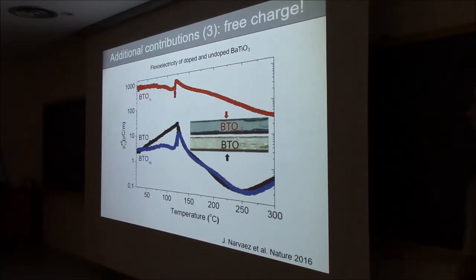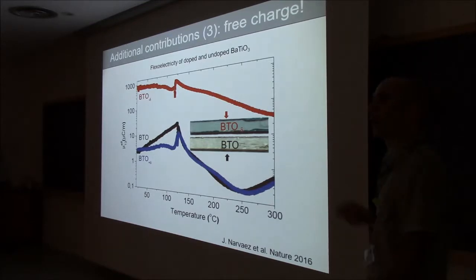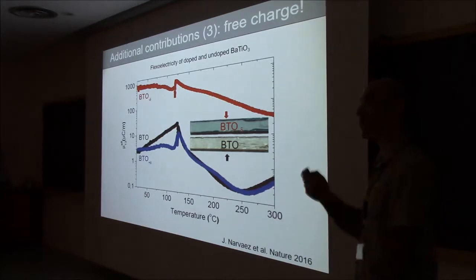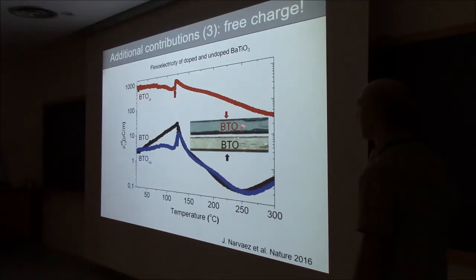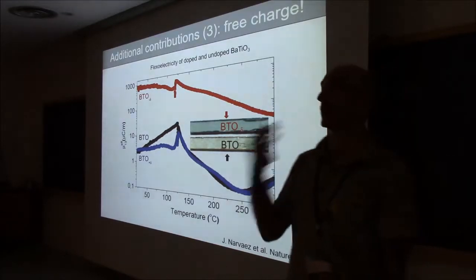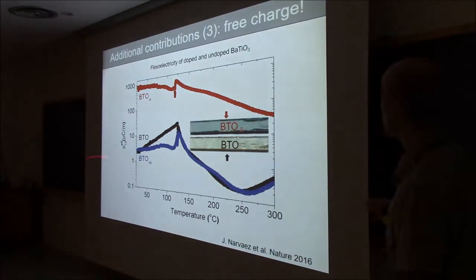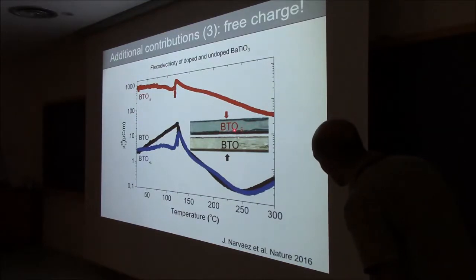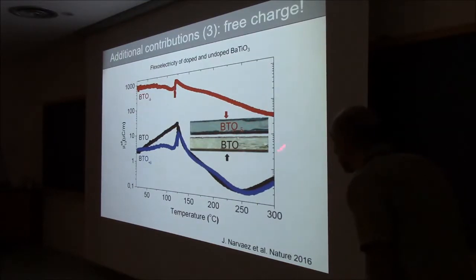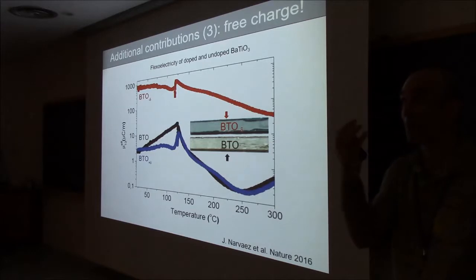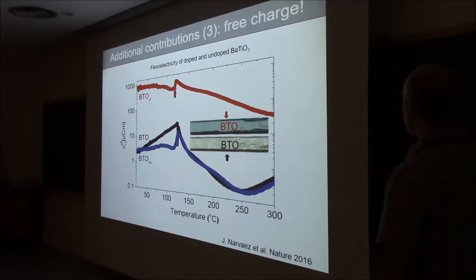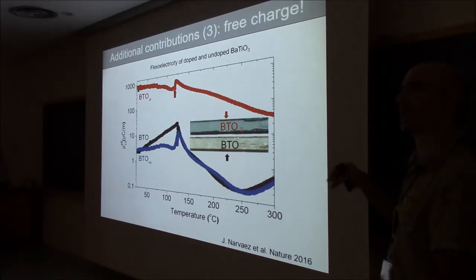So we thought, okay, this probably comes from leakage. Let's see how far we can push it. Let's make our BTO super leaky. You can make it very leaky by putting it in a reducing atmosphere, taking oxygen out. If you take oxygen out, it will become oxygen deficient, obviously, and it will become visibly darker, bluish. If you do this with STO, it can become almost black.